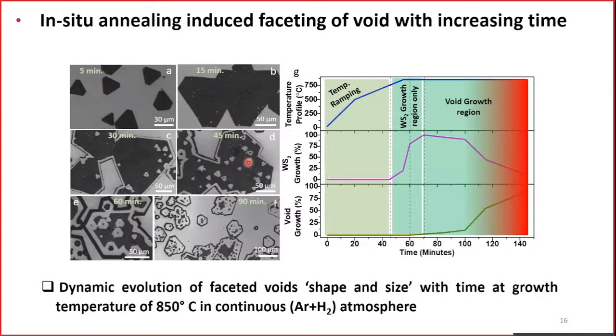We also looked at the kinetics of the faceted void formation by systematically changing the annealing time. At 5 minutes, you have almost a perfect 2D material. At 15 minutes of post growth, you see small void formation. And as a function of time, 30, 45, 60, and 90 minutes, your 2D material is almost completely thermally etched. We also made a clear process window. If you want to get 2D material without defects, this is the profile for a particular temperature of 850 degrees Celsius. Somewhere around 60 to 70 minutes, the growth essentially saturates.